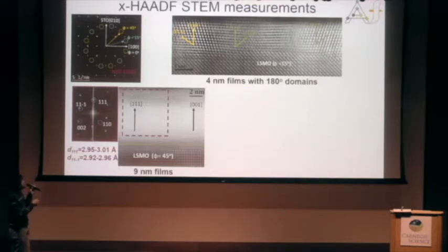In thinner films, we do see a domain structure. Here I'm showing 180-degree domains. And in thicker films, we in fact see the evolution of not just 111 out of plane, but domains with 001 out of plane. And this is perhaps the reason why the polarization of this is less than the polarization of thinner films.